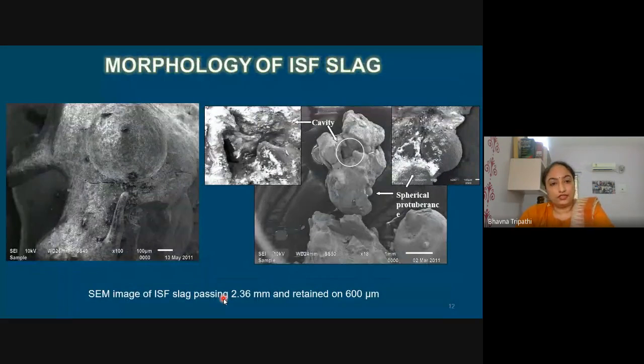Morphology is very, very different. This picture is very interesting. You can see there are needle-like eruptions or spherical surfaces in ISF slag, and the reason is because it is quenched. The slag comes from the furnace at high temperature, it is molten at that time, and it is rapidly quenched in water, and that is why this irregular kind of structure and fragmented particles are formed.